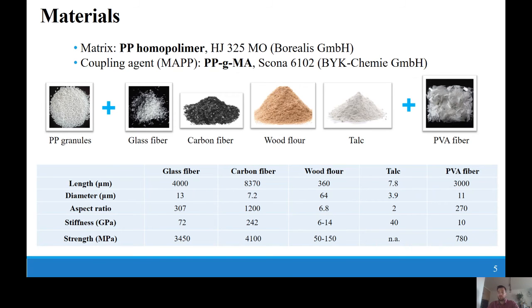Polypropylene hybrid composites were prepared by the combination of traditional reinforcement, wood, glass, carbon, and talc, and polyvinyl alcohol, PVA fibers. Impact resistance is improved because the presence of these flexible polymeric fibers increases the number of potential energy absorbing mechanisms in the composites. Interfacial adhesion was regulated with the use of maleic anhydride modified PP, this is the MAPP. The composites contained 20 weight percent of traditional reinforcement, and the amount of PVA fiber changed from 0 to 40 weight percent in them. The most important characteristics of the reinforcing fibers are collected in the table below.